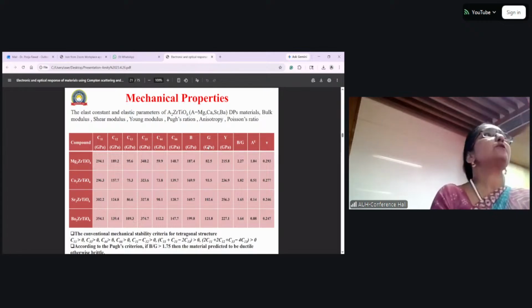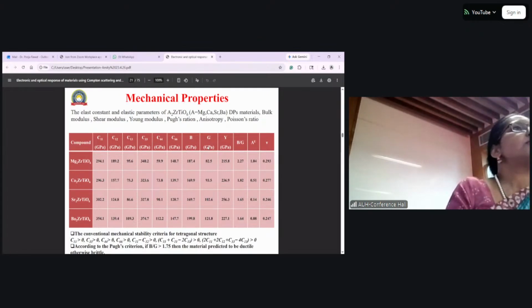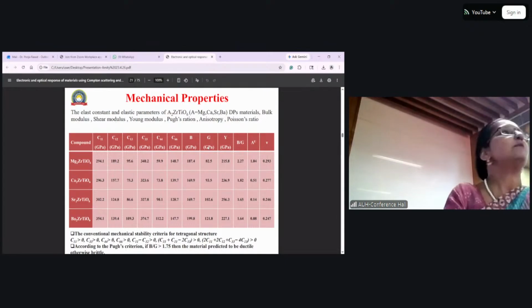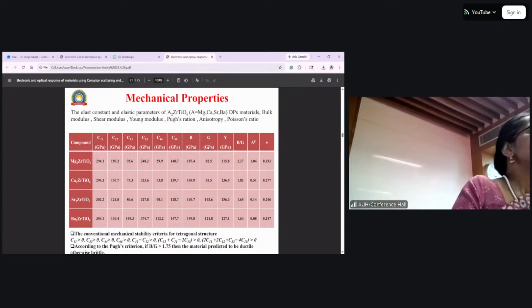Then we check whether the material will be suitable for practical application. We need to check whether it will be able to sustain or survive if we apply certain kinds of stress, deformation, or pressure. For that we calculated certain mechanical parameters of these materials: the Young's modulus, bulk modulus, and shear modulus, which define the different kinds of deformations, and the anisotropy, and whether the material will be ductile or brittle. If it is brittle, it won't be suitable for practical application. All the compounds have good values of all the moduli, whereas the B by G ratio defines whether the material will be ductile or brittle. If it is greater than 1.75, the material will be ductile. Otherwise it will be brittle.